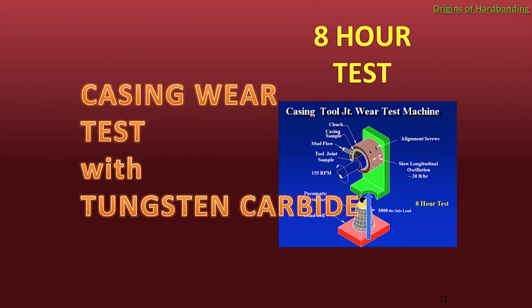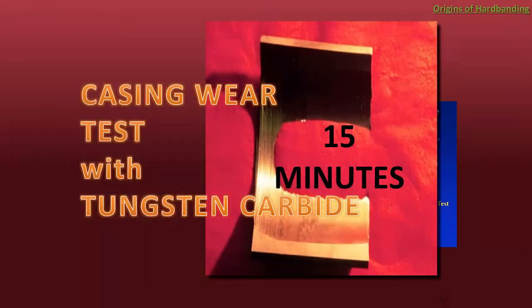Allow me to elaborate on the use of tungsten carbide in cased holes. The casing wear test verified the problems noted in the field when tungsten carbide was used in cased holes. As mentioned, the casing wear test is an 8-hour test. The mild steel and tungsten carbide lasted only 15 minutes. The result of this test convinced many operators and drilling contractors to ban tungsten carbide hard banding products in any cased hole, or in some cases, any hole, and embrace the casing-friendly products such as DuraBand.